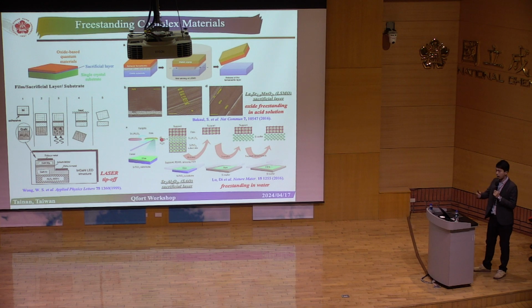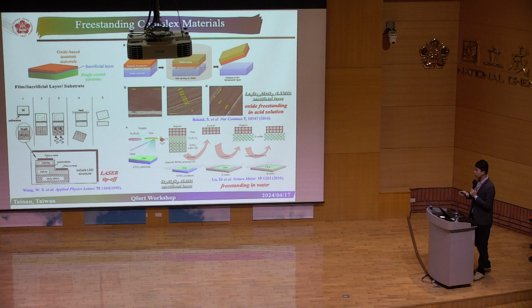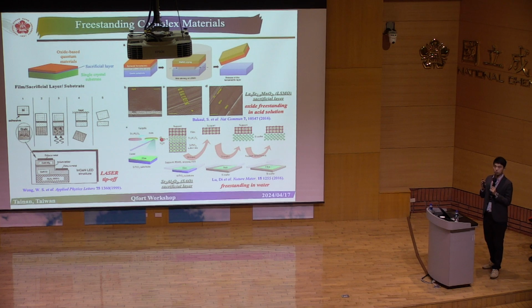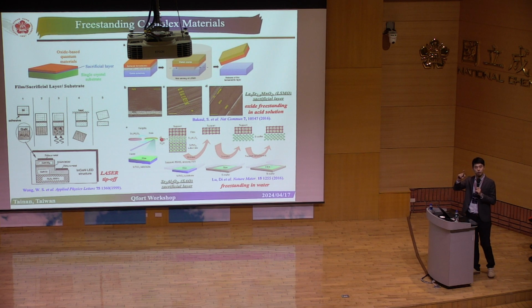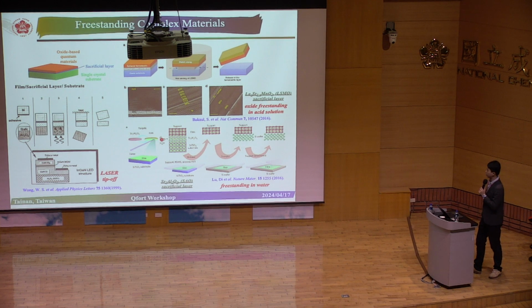Luckily, if you look back to about 25 years ago, there is a process in semiconductors called laser lift-off. Basically, you make the epitaxial structure, and you have a laser, and you bombard or break the interface, so that you can get the freestanding membranes. However, during that period, the damage to the surface or to the interface was too severe. So you can only get micrometer thick films. It was very, very hard to make them into thin films.